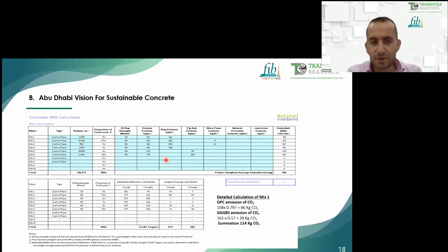Let's go through, as an example, the calculation for the grade 25 MPa. It's representing 6%. This mix consists of 270 kilograms total of cement and cementitious material. We have 108 for the OPC and 162 for GGBS. OPC, as we got from the reference data table, 108 multiplied by 0.797, we will get 86 kg of CO2 emission. For the GGBS, 162 by 0.17, we got 28 kg.